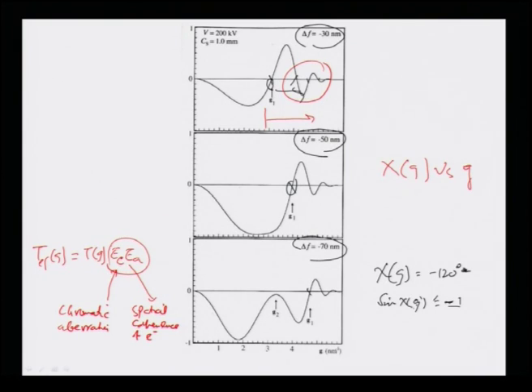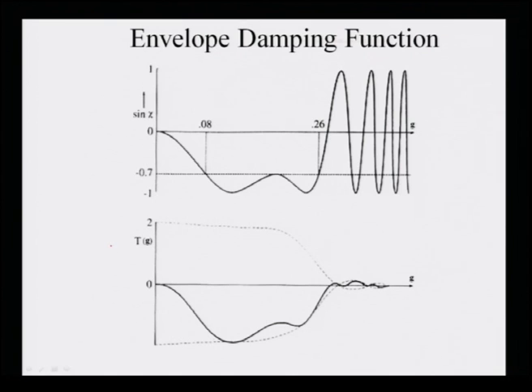And this is what is shown there. As you see here, this is sine chi as a function of g. There are many such higher order frequencies, or higher order d values, which get damped out because of the presence of these envelopes due to EC and EA. So the effect of EC and EA is to damp out the higher order frequencies. So we cannot access them.